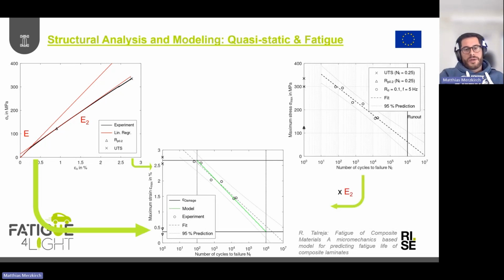Some tests have been done stress-controlled here at fully tension loading, at 5 Hertz so that the specimen doesn't heat up too much. You see the results of the quasi-static testing and a proper S-N curve where we defined the run-out at a million cycles. Now how do we get to the strain-based curve? Since the stress-related values were in the upper region, we used the second slope here, and here we go. It's actually a coincidence, not a coincidence, but very comparable results between the model and the experimental part.